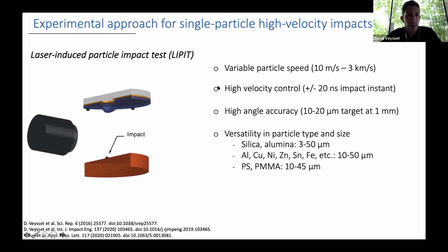So using this method, by changing the laser energy, we can vary the particle speed from tens of meters per second up to a few kilometers per second, and because it's optical, everything is optically controlled. We have high repeatability, high reliability of the impact events. So we know with good precision, with nanosecond time precision, the impact instant. So we can trigger the camera and look at the right timing.